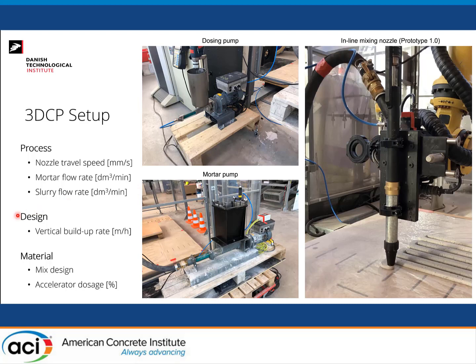And then there is information, of course, from the design side. Depending on which geometry and speeds I'm printing, what's the vertical buildup rate I'll be operating with. And that vertical buildup rate will point back into which structural buildup we need for the material. That comes to the last part. In that one, we have a base mix design which is heavily retarded, and then what I call the accelerator dosage, but it's really an activating ingredient dosage, because it's not a shotcrete accelerator, as most people would associate when they read the word accelerator.